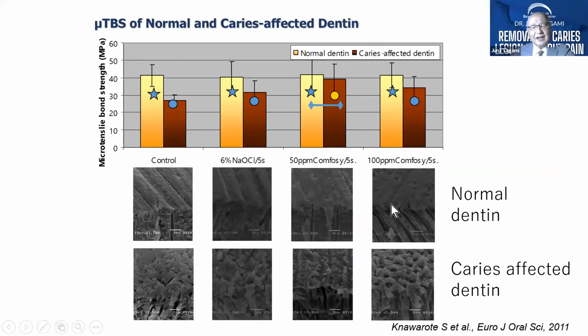Of course, the smear layer at normal dentin surface and the caries affected dentin is very much different because of much more organic phase in the case of caries affected dentin. The so-called mud-like smear layer is produced. That's why the removal of the organic phase from the smear layer is very effective to improve the penetration of the material. We call this kind of treatment smear layer deproteinization.